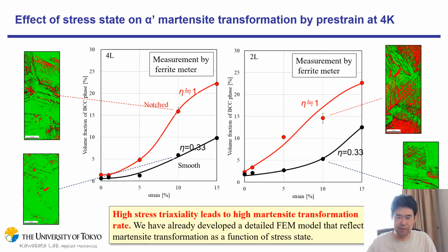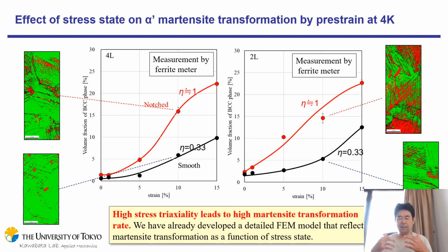This is the experimental result. The martensite transformation rate measured by ferrite scope is shown here. High eta, where eta is the stress triaxiality factor index, specimens show a remarkably high transformation rate, even at the same plastic strain condition. And the EBSD analysis also shows higher martensite transformation at high stress triaxiality. This is against some previous studies and agrees with some previous research, so this range has remained unclear. As a result of our study, high eta brings a high transformation rate of martensite.